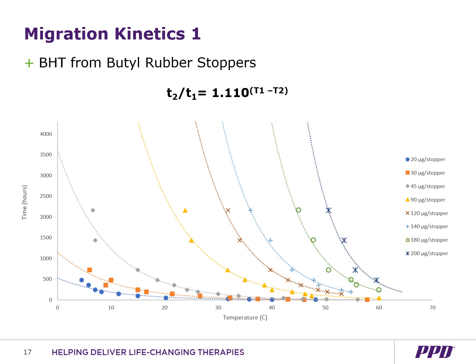Using the equations generated from each of the curves plotted, a generic third model was developed that could be used to predict the duration of the study required to achieve a certain amount of extractables at a given temperature, where you have T2, or the predicted duration, over T1, the reference time interval, is equal to the constant 1.110 raised to the power of T1 minus T2, or the reference temperature minus the accelerated temperature.